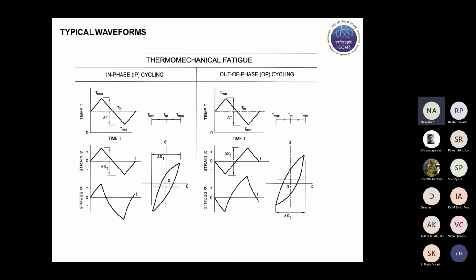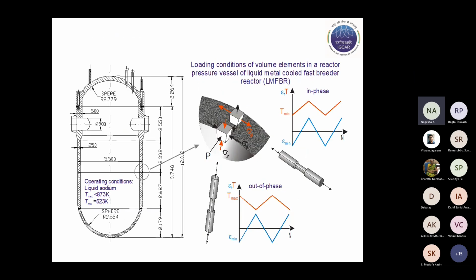While carrying out TMF, there are two extreme and basic temperature-strain waveforms deployed. One is called IP cycling, wherein with the temperature increase, the strain goes from peak compressive strain to peak tensile, whereas out-of-phase is exactly the opposite situation. In practice, there could be a different phasing relationship between the strain and temperature in service. For example, this is representative of a volume element of a high temperature component. In this case, maybe you can say it is a liquid metal cooled fast reactor pressure vessel, wherein on the outside surface we see an in-phase